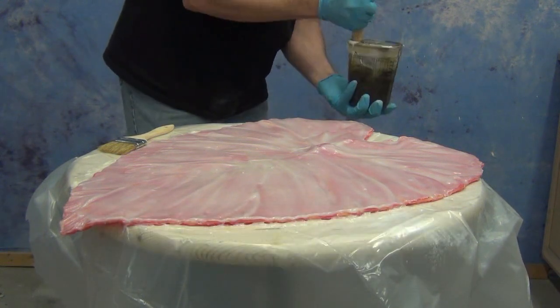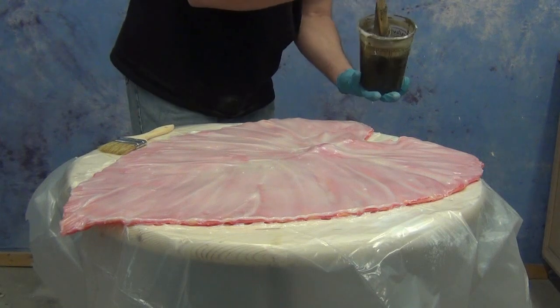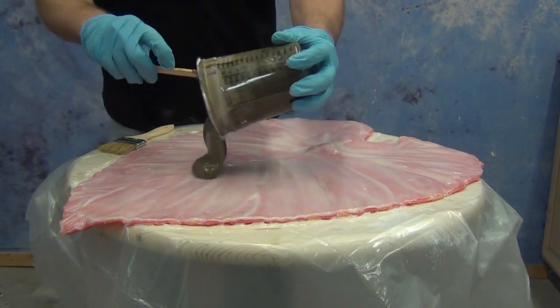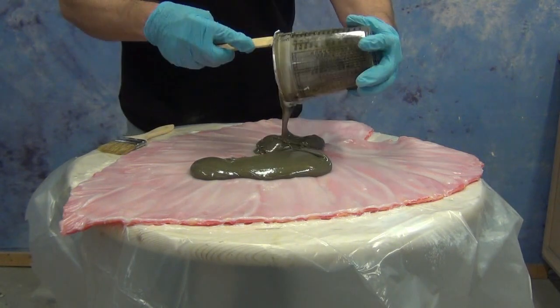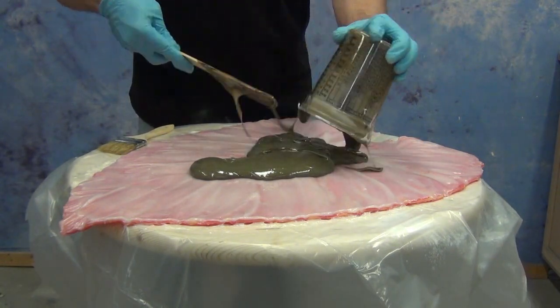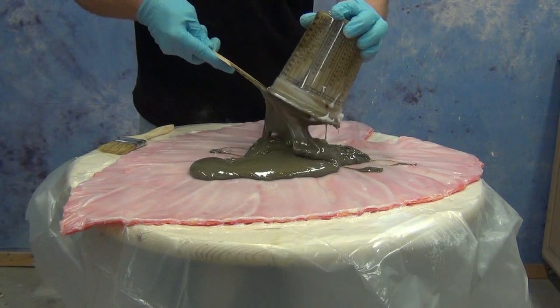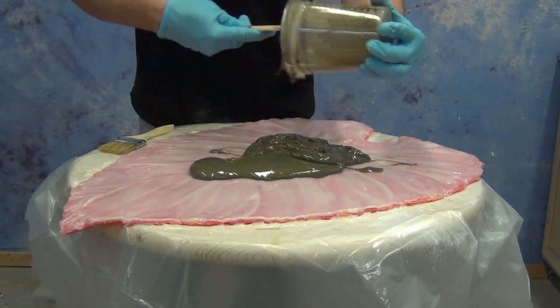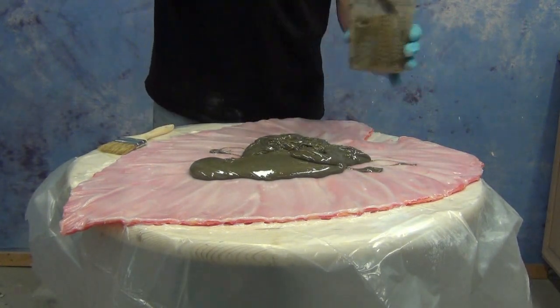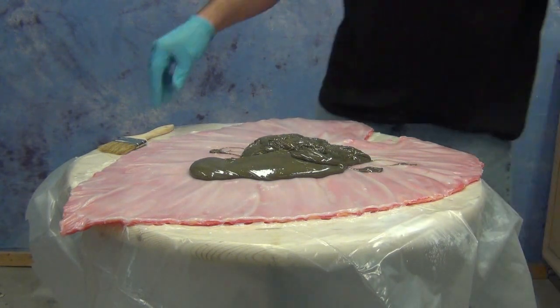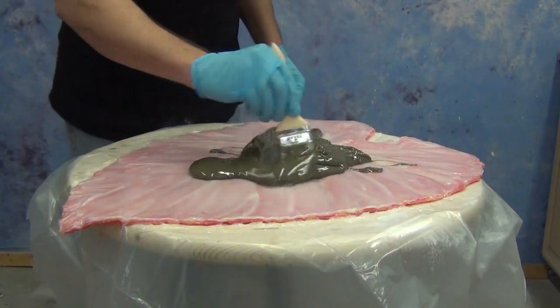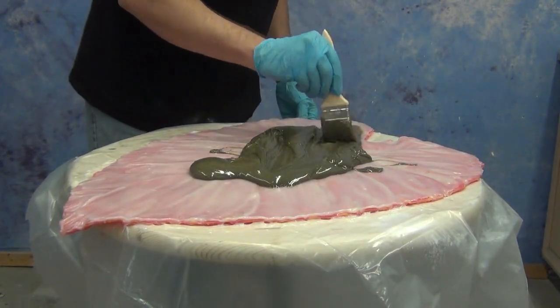And we applied the second batch at about 1 hour after the first batch was applied. So the first layer was still a little bit on the tacky side, but it wasn't pulling up when you touched it. And that's important there. We don't want to disturb that first batch by applying the second batch. So when in doubt, wait just a little bit longer and apply it, say in an hour and a half, 2 hours if necessary. Now again, we're going to brush that all over the surface of our mold.